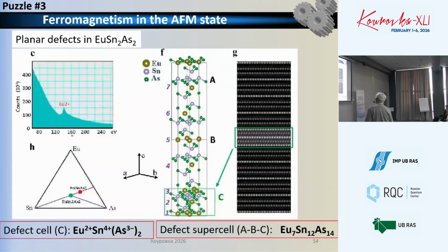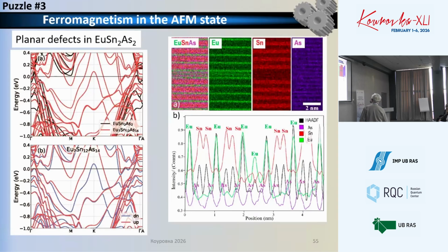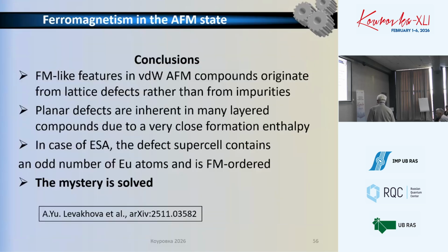Immediately, we tested the valence state of europium, because europium can have a different valence state. Nothing unusual here. It's the standard 2+ oxidation state. And just by decomposing this defect, well, this picture shows how by doing micro EDX scanning, you can see what is going on here with the europium distribution, tin distribution, arsenic. So the europium atoms exhibit an additional row, tin is missing here, and arsenic is usual. And here the profile of this scan showing the picture in detail.